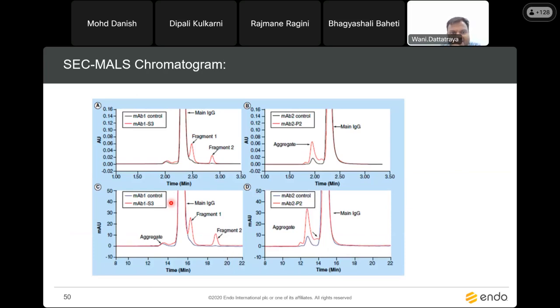This is some of the data of the size exclusion chromatography of proteins. This is the main protein peak of the immunoglobulins. If you are getting any peaks here, like this in the red, suppose you are seeing fragment 1 or fragment 2, these are the truncated peptides. These are degraded and showing the truncation. In the control, that impurity is at a lower level, but if you compare with this real-time aged sample, you get this truncated peptide, but there are no aggregates here. If you compare this second formulation, the truncated peptides are not there, but you are getting the aggregates. Same with this also. So from this we can conclude what is forming, whether truncation or aggregation, that we can determine by this technique.